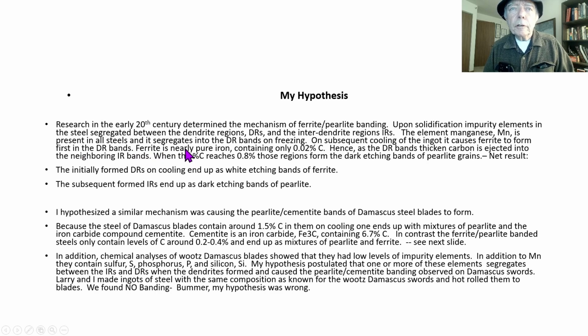Now, ferrite, since it's nearly pure iron, it ejects all that carbon into the surrounding bands. And when it gets up high enough, around 0.8 or just a little bit below actually, pearlite forms. Those regions are dark etching. So the net result is this. The initially formed DRs, that formed when the dendrites formed, on cooling, end up as white etching bands of ferrite, and the subsequently formed IRs of the dendrites end up as the dark etching bands of pearlite.